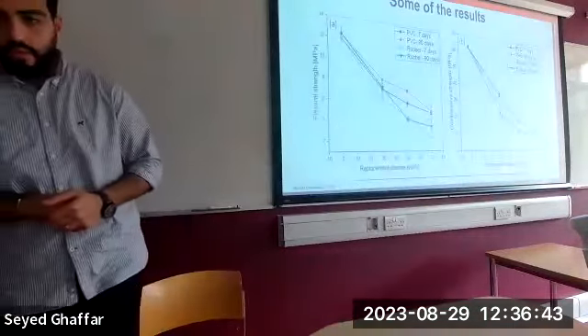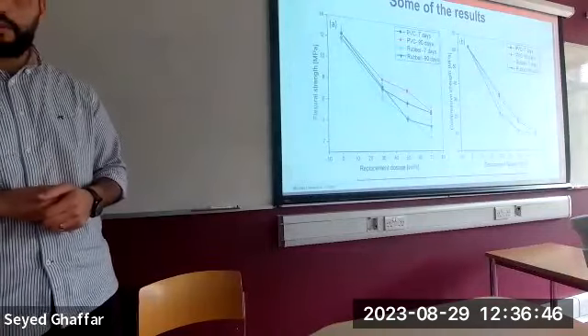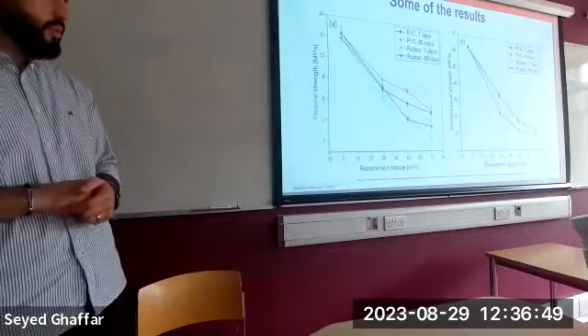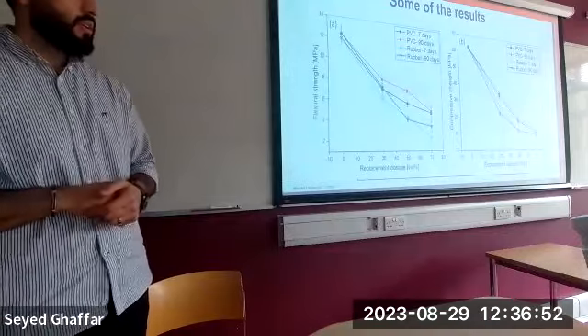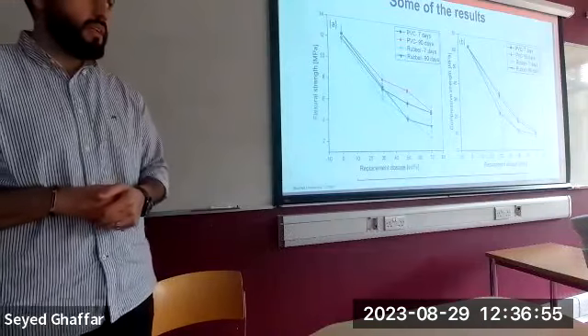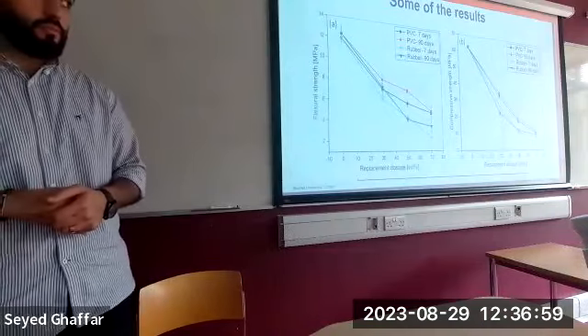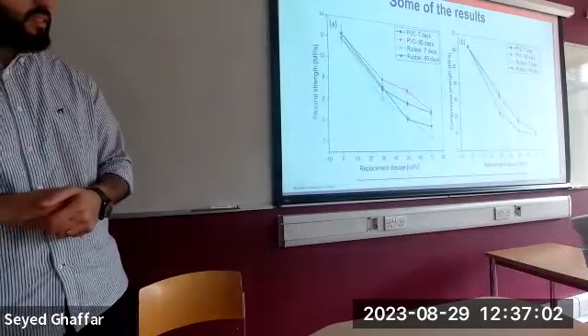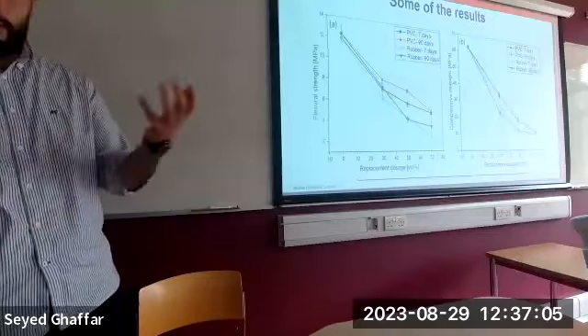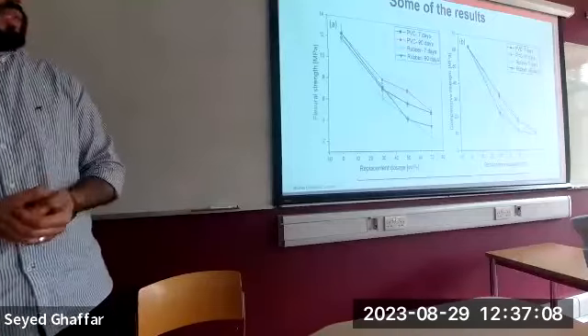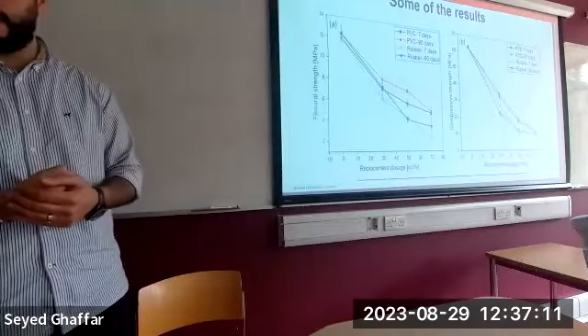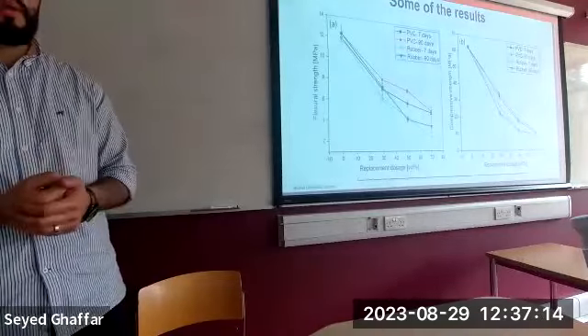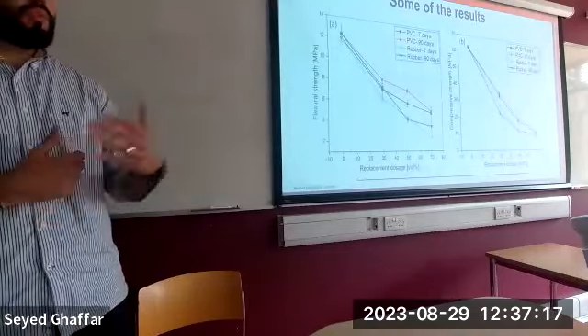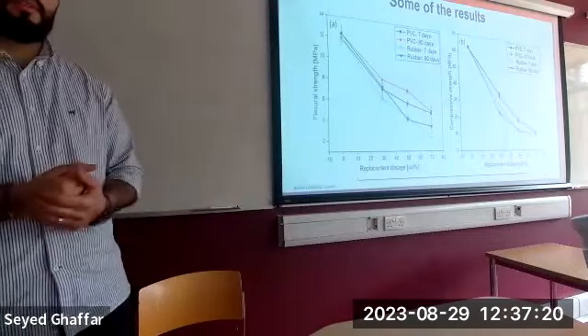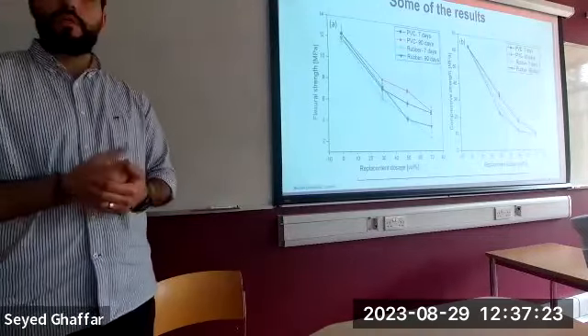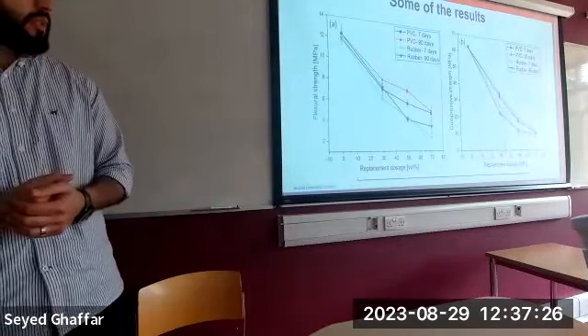We looked at the flexural strength and the compressive strength, and you can see that both reduce with increasing amounts of recycled aggregates. This is something to be expected. We are saving natural sands because our natural resources are scarce, and we need to think of alternative ways. So these graphs show that if you want to replace sand with recycled aggregates, you need to focus on non-load bearing structures and other applications, such as noise reduction walls and pavements in recreational areas in parks, because they have very high impact and energy absorption.